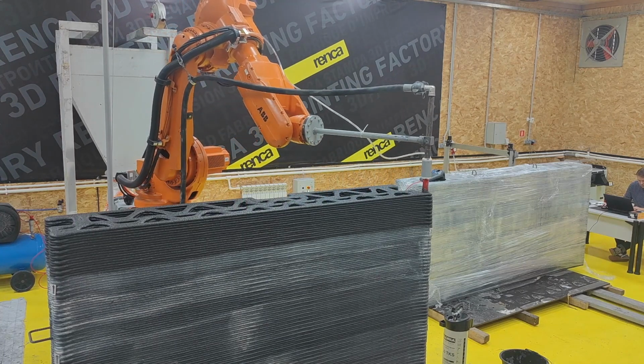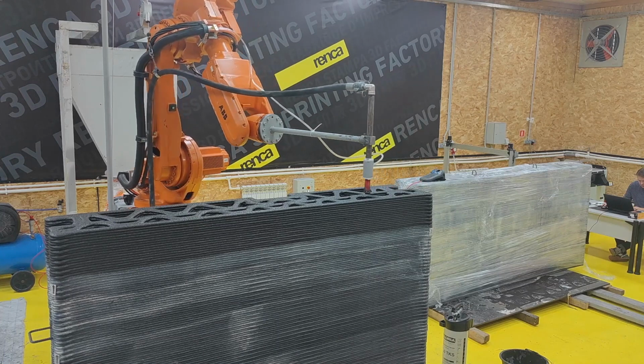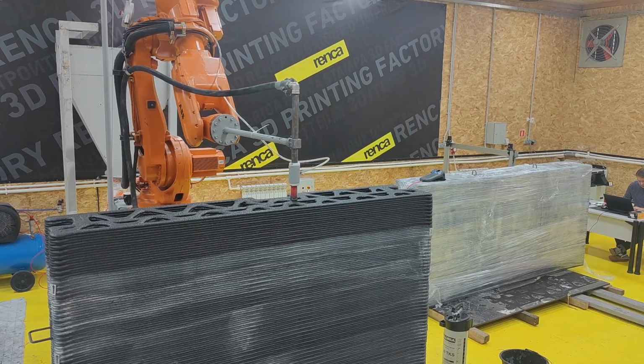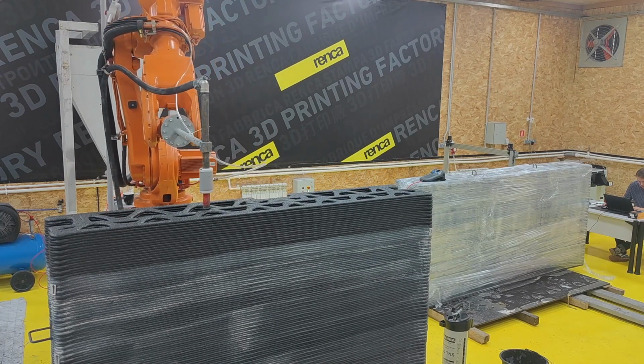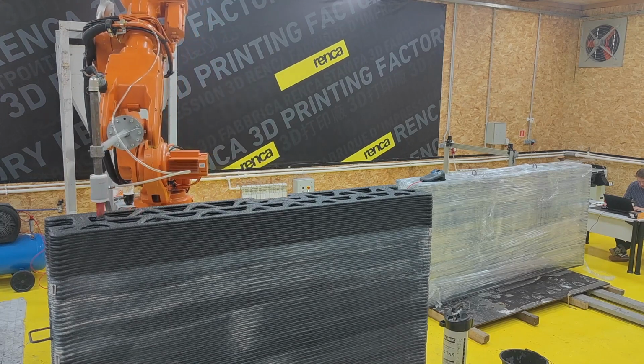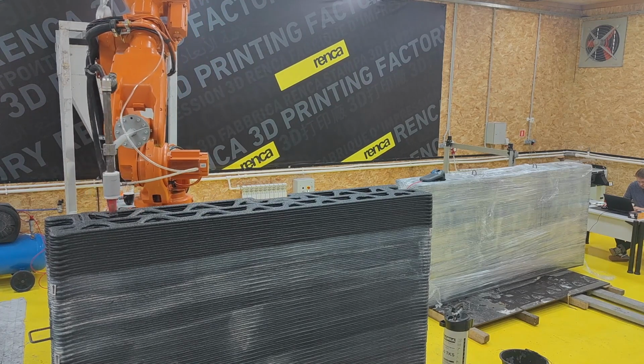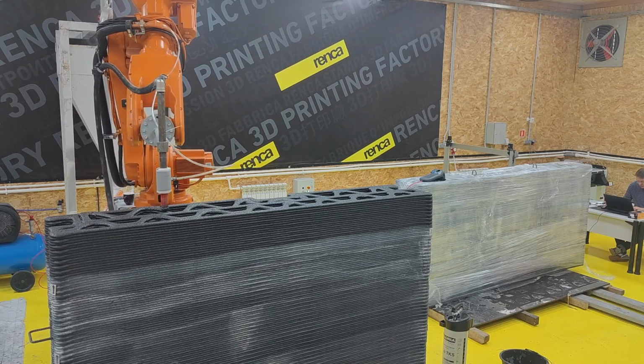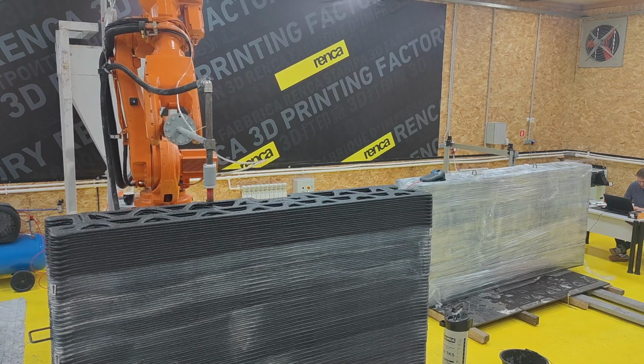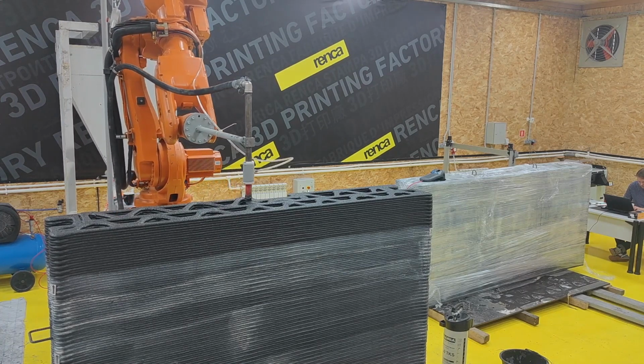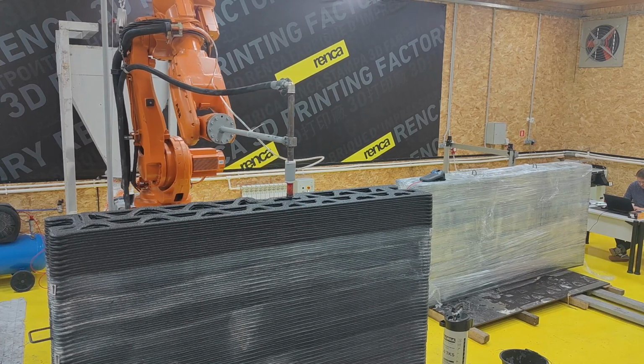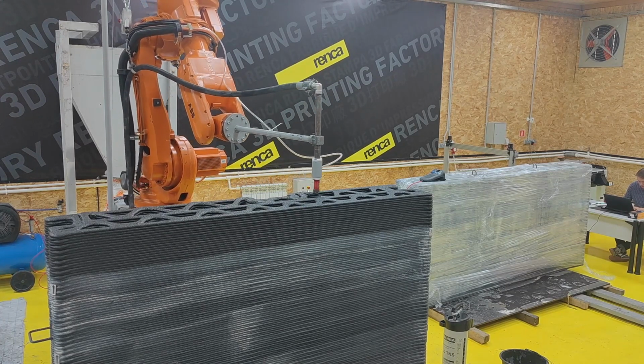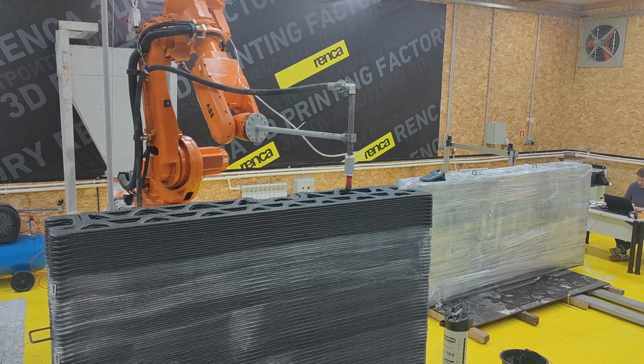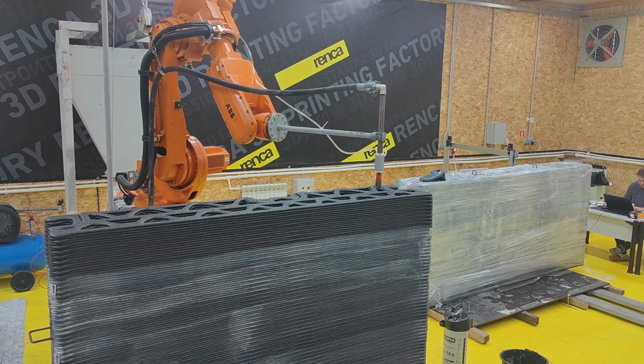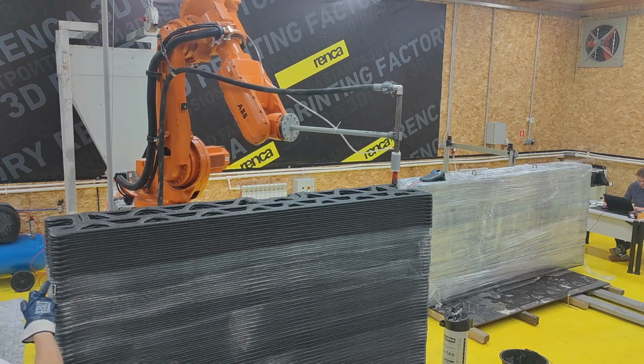Very interesting. Is there a tarp over it at any point? Do you want to maintain humidity, or the water's all leaving so quickly? No, we don't need to maintain humidity, unlike Portland cement, in order to avoid the cold joints. Here we have adhesion in between layers, thanks to the geopolymer interaction of atoms. So you can move the object within a few hours, and then how long do you have to wait until the dehydration process is complete?